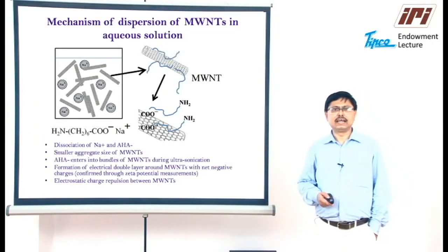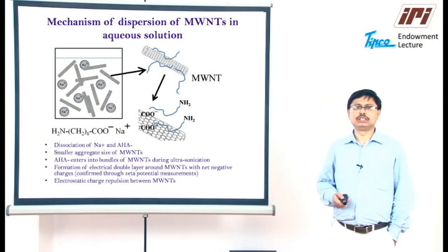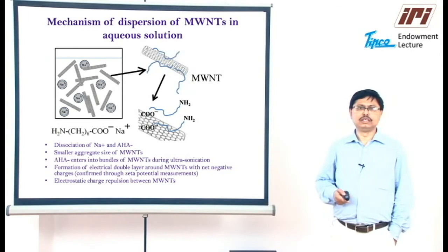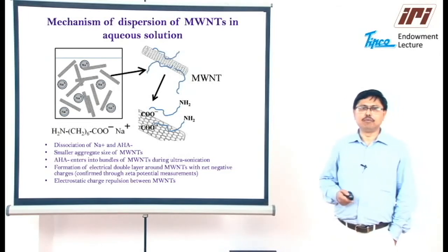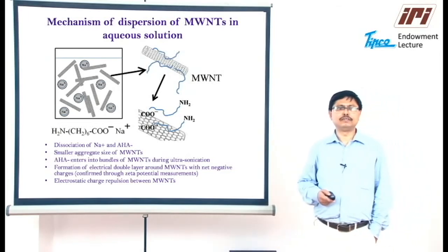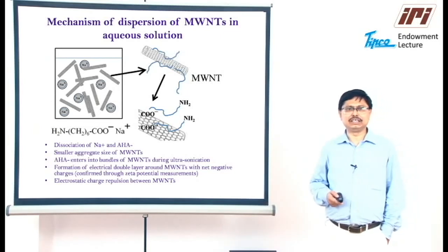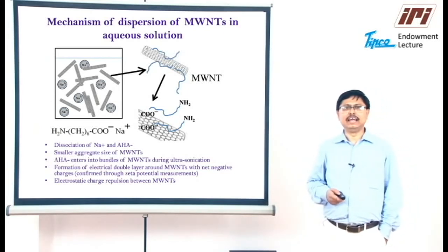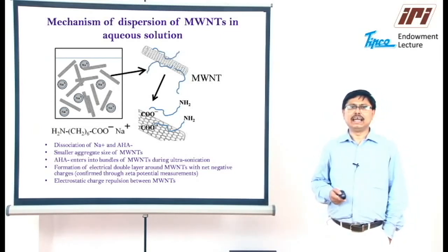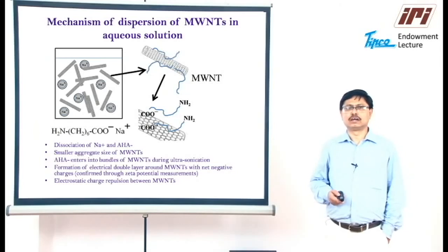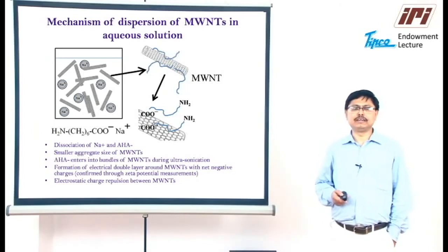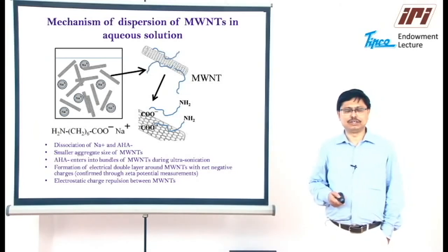We need to understand the mechanism of dispersion of multi-wall carbon nanotubes in aqueous solution. The multi-wall carbon nanotubes were modified with the NaHA modifier in view of the fact that any covalent modification would disrupt the electronic structure of the nanotubes and would involve breakage of the nanotubes during the functionalization process.